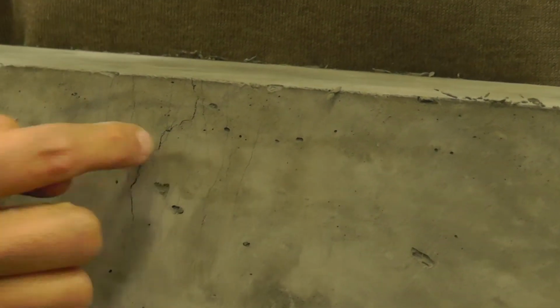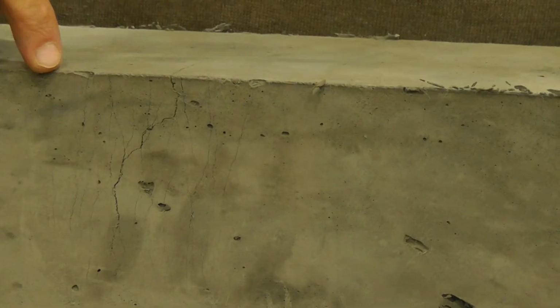So these are, again, flexural cracks emanating from the loading where we loaded the roller. Okay, so these are all the flexural cracks. And if I flip the beam this way, you can see the cracks which you saw on the bottom side of the plate. So these are basically these cracks as seen from the bottom. So these are basically crack planes, this crack throughout the beam, which you can see on this side as well.